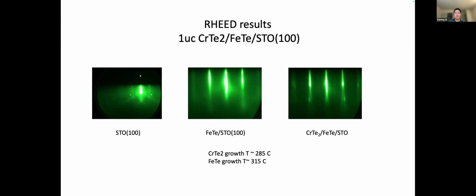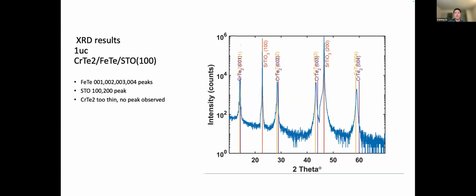After adding 1 unit cell of chromium ditelluride, the RHEED pattern stays sharp and develops a bottom fork, which indicates that chromium ditelluride has formed. And the growth temperature for chromium ditelluride, the substrate temperature is 285, and for iron telluride, the substrate temperature is 315 degrees Celsius. So the XRD 2-theta scan of this sample, for iron telluride, shows 001, 2, 3, 4 peaks as expected, and STO substrate peaks at 100 and 200. But chromium ditelluride is too thin to give a clear peak.